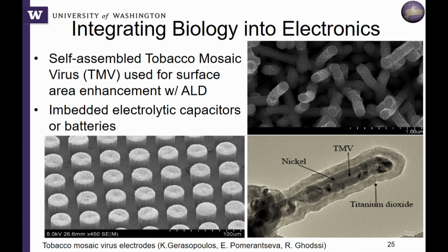And then we take things like our atomic layer deposition and we can coat those viruses. So you can see here this virus is the core of this shell. It serves nothing functional other than being a scaffolding to build on, okay? So it has no function. We put a titanium dioxide coating, we then put a nickel coating, and then we can put another titanium dioxide, and that forms our dielectric barrier.